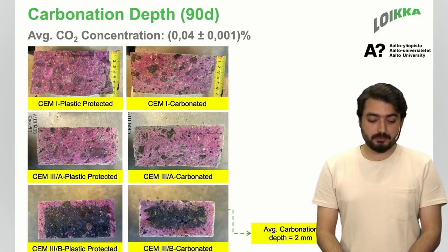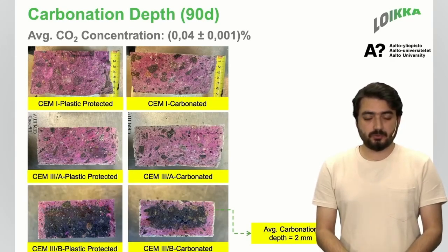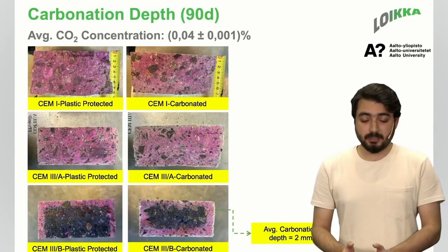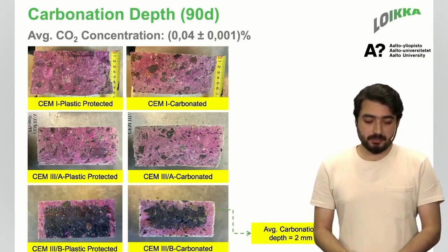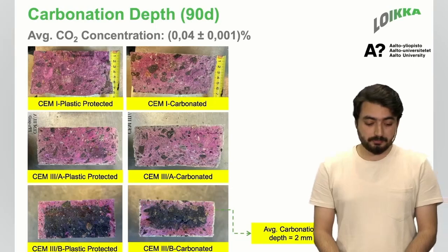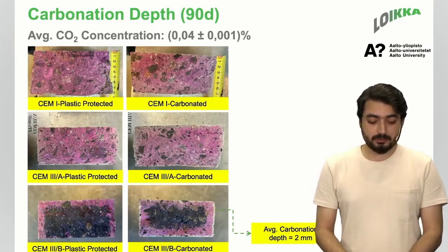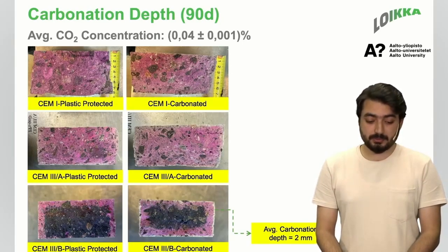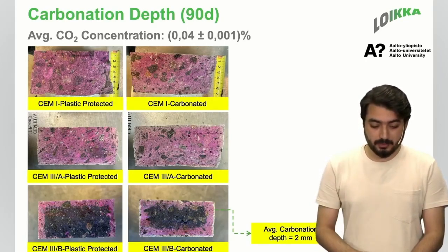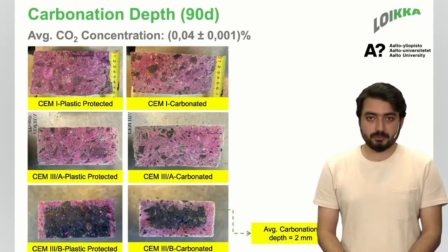If we move forward to CEM III/A, it had a couple of decimal points of carbonation depth measured. It was basically not measurable at this point, so we will get to know once the concrete is aged enough, basically 6 months or after 1 year. And for CEM III/B, here we can see that the carbonated sample, which was not plastic protected, I managed to measure the CO2 carbonation depth, and here you can see a clear border around the sample, and it showed an average CO2 carbonation depth of 2 millimeters.